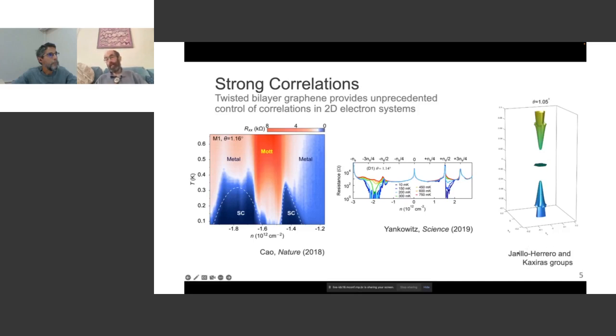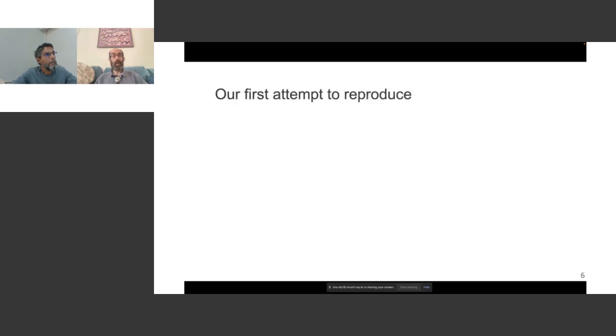And in fact, when more careful calculations were done, considering how the two layers could adjust each other, one layer to the other, and move their atoms around to find a lower energy configuration, avoiding that AA stacking that I talked about, it turns out not only should the band become flat, but it should actually become separated from other electron states by a substantial gap. And so this was really an exciting system, and my group tried to reproduce this.